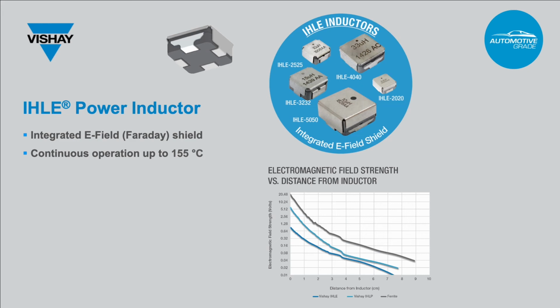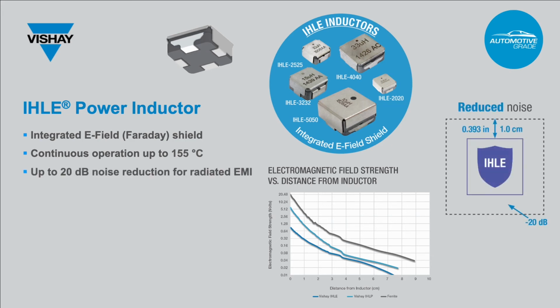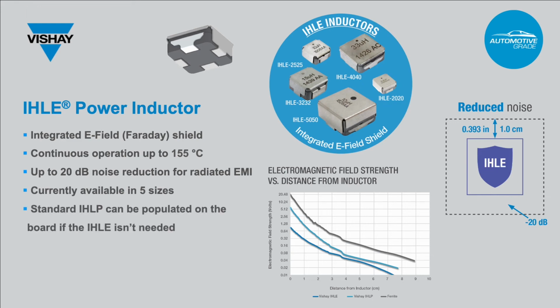In contrast, using an IHLE from the beginning of the design, or swapping out an IHLP if the printed circuit board has already been laid out with the 2 additional terminals for the shield, can be a quick and very cost-effective solution. The results will vary from one design to another, but reductions up to 20 dB in the radiated electric field, when measured at a distance of 1 centimeter above the center of the device, have been achieved. The IHLE is currently released in the 2020, 2525, 3232, 4040, and 5050 sizes.